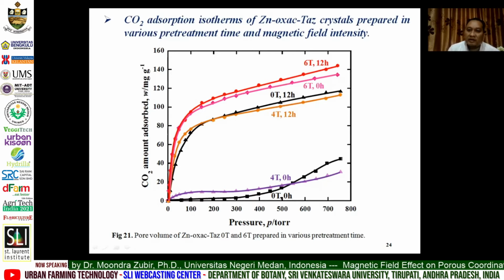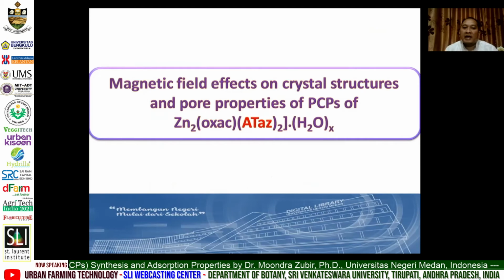But interestingly, for 6 Tesla, it already absorbs the CO2 even with no pretreatment temperature. Then after 12-hour pretreatment temperature, the 6 Tesla also absorbs the highest carbon dioxide if compared with 0 Tesla and 4 Tesla. And then the second similar PCP is also synthesized as zinc oxac ATaz.